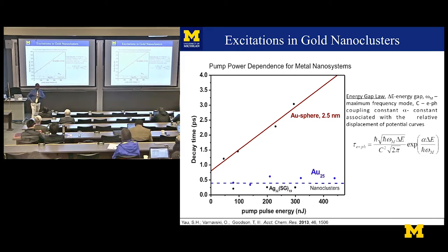There was no dependence on it. You increase the power as much as you want. If the resonance is not there, no dependence on the lifetime. This is the first evidence of some idea that you could have a band gap kind of relationship. And so instead of just having a relaxation process proportional to temperature, it's actually proportional to the actual gap of the energy, if there's a gap that exists.